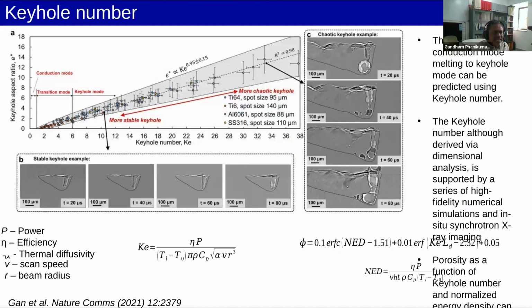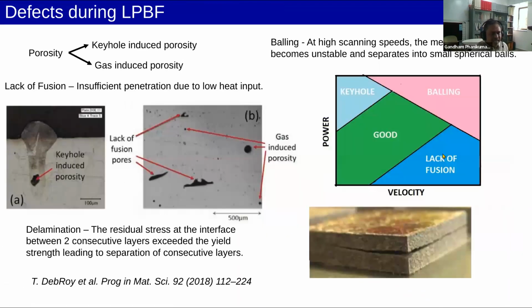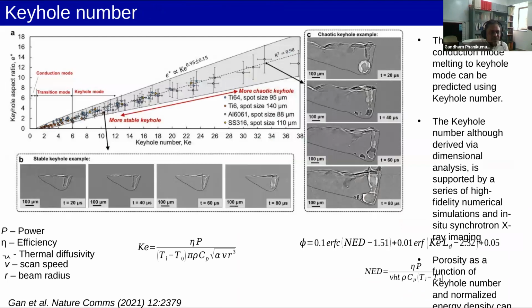Okay. Now there is another concept that has come in the literature, again from this year's latest paper, on what is called the keyhole number. Basically it is explaining this particular diagram. This diagram is originally empirical, and it has been explained in a phenomenological manner by using the likelihood of keyhole formation as a function of the parameters used for the laser. So you have laser power, efficiency of absorption, the thermal diffusivity, the scan speed, and the beam radius. These are all used to comment on how keyhole formation can happen. And the keyhole number will tell the probability of formation of the keyhole. If it forms, it means you're likely to have porosity due to that.